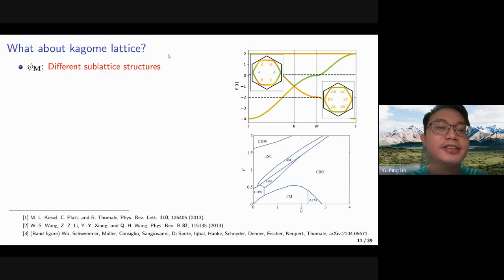So the next case we're going to look at is the kagome lattice. For kagome lattice, we have 3 bands where one of them is flat. And there are 2 Van Hove singularities that occur on the 2 finitely dispersing bands. It turns out that the 2 Van Hove singularities have different sublattice structures. For the upper band, we'll see that each of the saddle points only enjoys the contribution from one sublattice site. Like this saddle point has it from A sublattice site, and this from B, and this from C. Meanwhile, for the lower Van Hove singularity, each saddle point will have 2 sublattice site contributions. So this will lead to different types of instabilities.